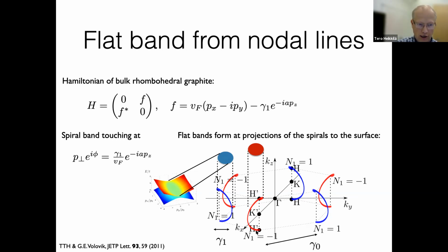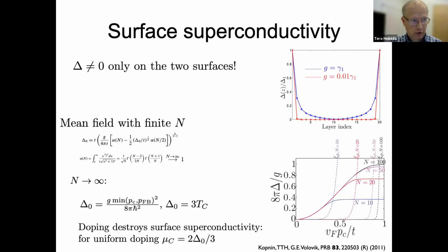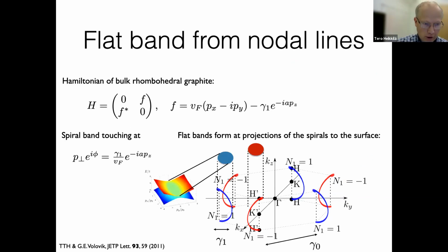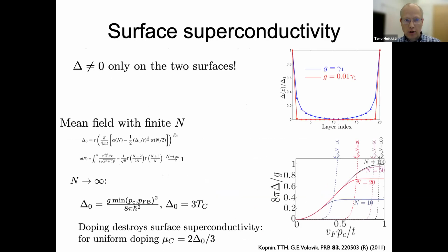If you look at what happens at the surface, you have a projection of these nodal lines on the surface, which describes this flat band. So this is the zero energy state due to the topological bulk-boundary correspondence of these nodal lines. Here they are called flat, but I will come in a moment to what happens once you include higher order hoppings. But now you can plug in the attractive interaction and consider the superconducting state in this system.